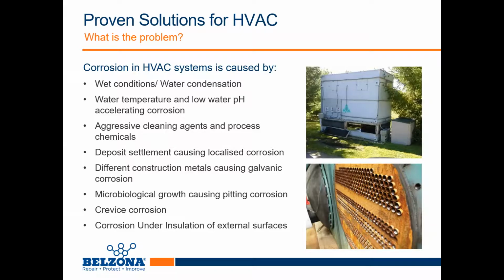Deposits. Low water velocity allows solids to settle and deposit on the metal surfaces. These deposits make it impossible for any corrosion fighting chemical to do its job. The protective film provided by the corrosion inhibitor settles on the deposit rather than on the metal surface. As a result, localized corrosion can thrive unchecked underneath these deposits.